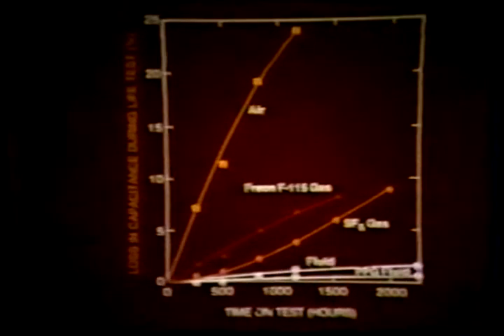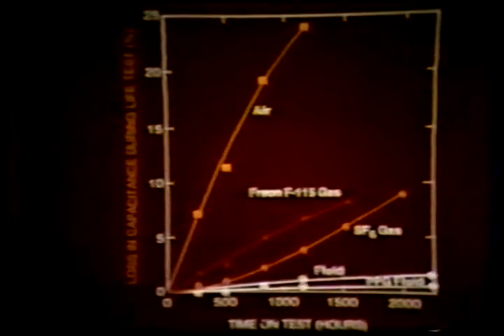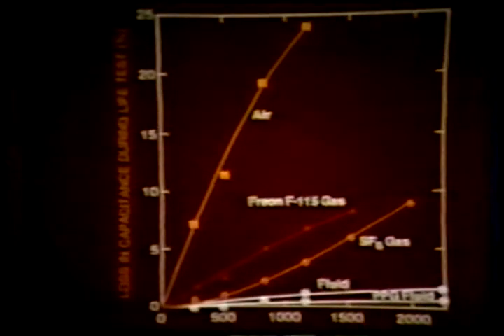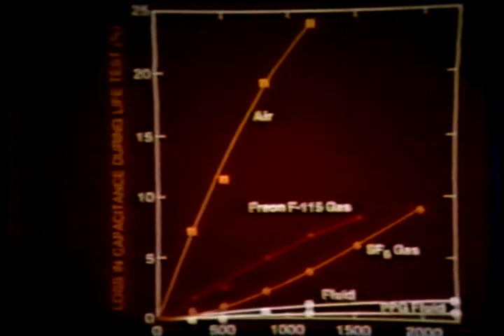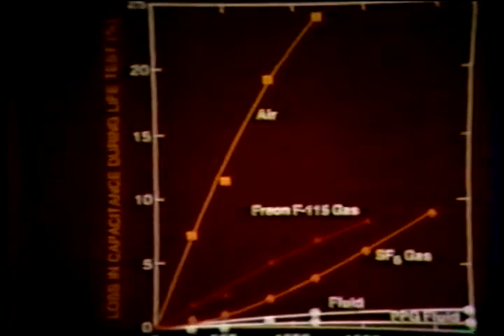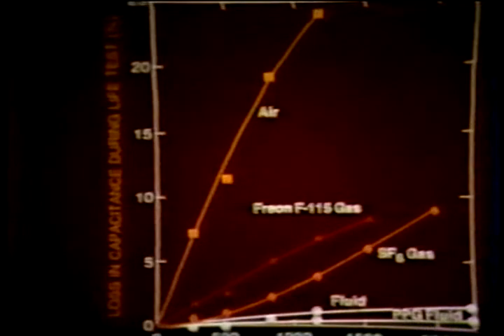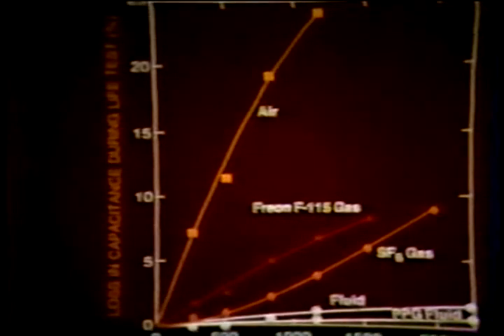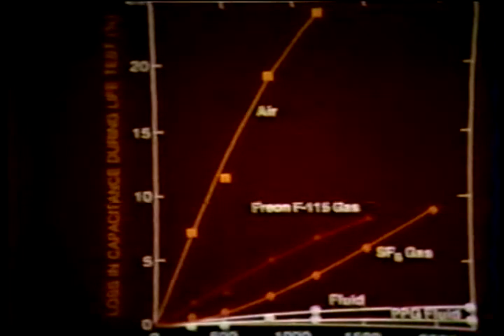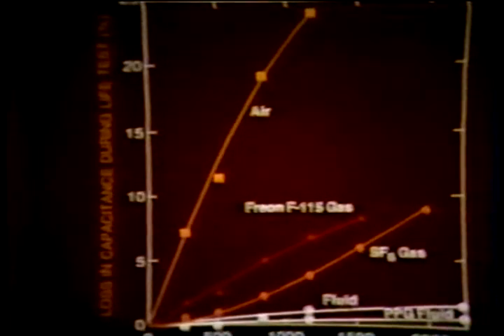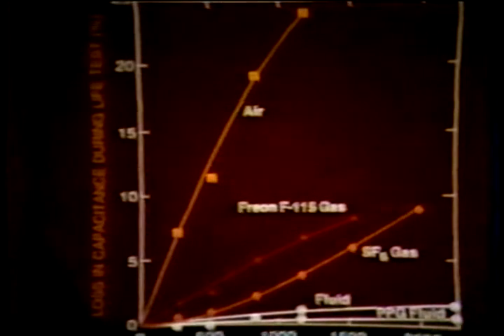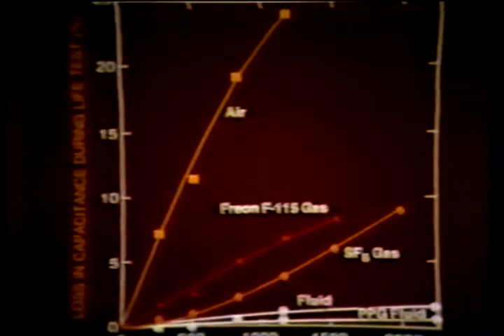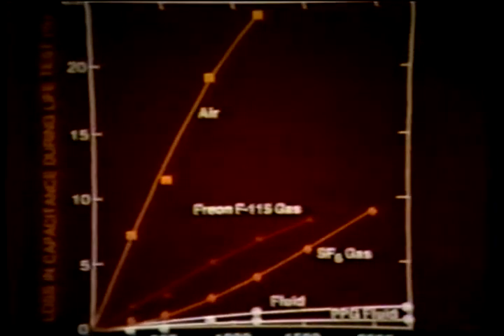In the case of a dry capacitor, in which only air fills the roll, a large and rapid reduction in capacitance is observed. If one would monitor the number of clearings during this test, we would find that this capacitor is undergoing continuous and high levels of clearings. We can see that the number of clearings can be reduced and the capacitance stability improved by a high-strength gas, such as SF6 or Freon.